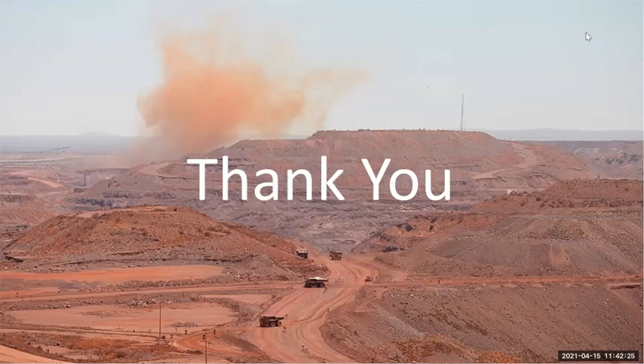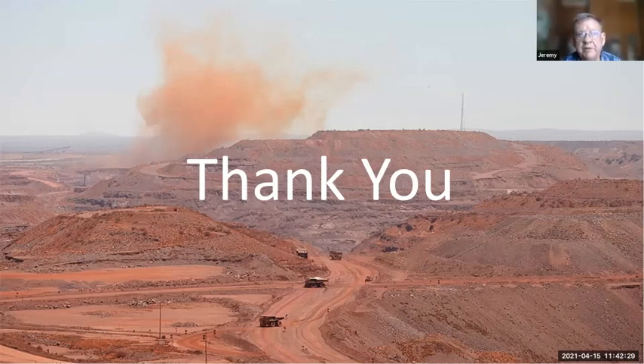Yes, Jeremy, please. Okay, so on the ROVOL, for those of you who are not familiar with it, it is a device that was developed by De Beers initially to track diamond breakage. What it does is it drops a particle through a number of cameras, and the cameras take pictures of the particle from different angles, and then the software builds up a 3D model of the particle, what they call a visual hull. Then the particle drops down, it gets weighed, and then it can go into a different density bin. So we have done comparative test work with IPP and the ROVOL on samples from a dense medium drum. And we're still in discussions with the guys at DebTech about the results.